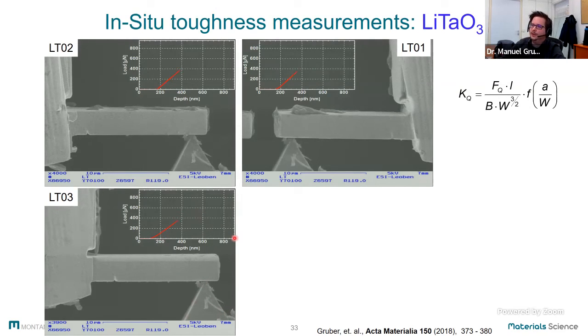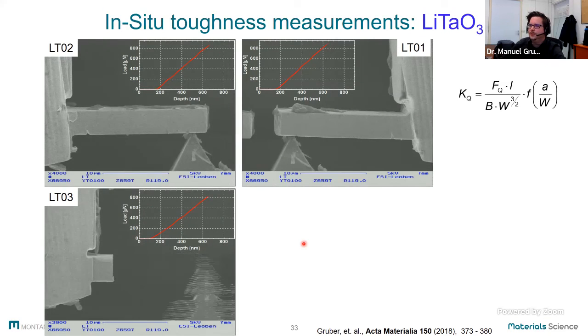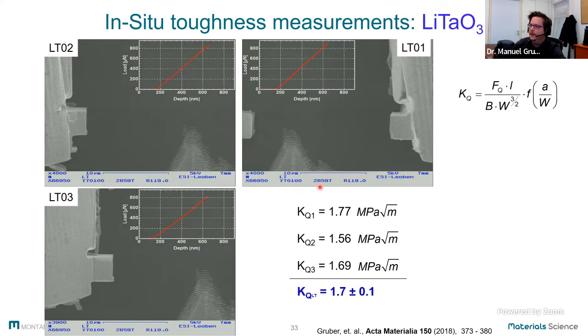We see a nice linear load displacement curve. And then we come to the point of fracture. We see no traces of plastic deformation. And so even for our small scale experiments, we see only brittle fracture. So these values can also be taken for larger samples and are comparable, at least the trend is comparable to what we observed first in our atomistic modeling experiments. And again, we can see that the toughness for lithium tantalate is higher compared to lithium niobate.